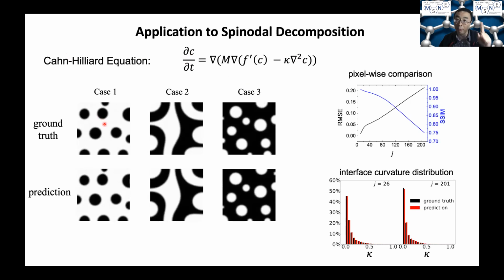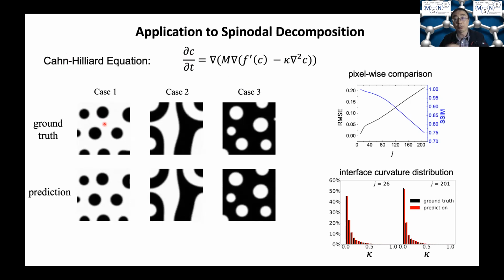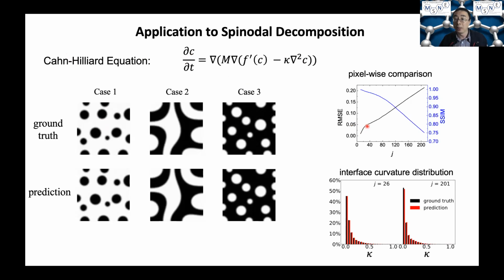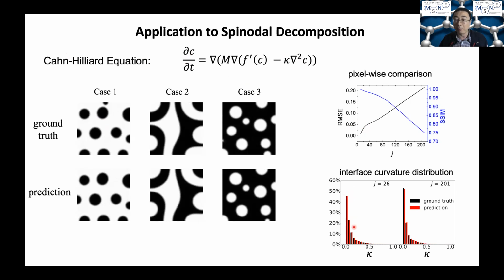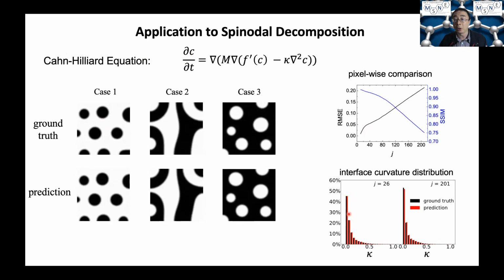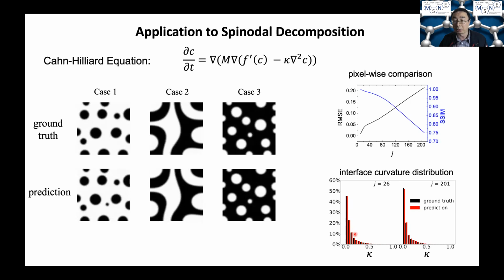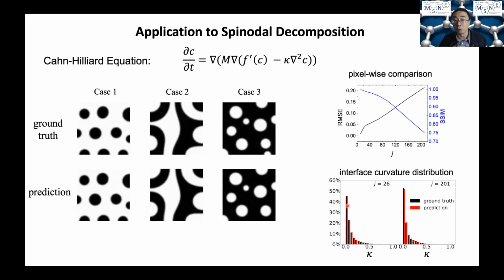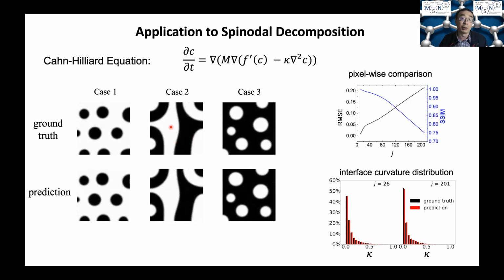When we use only 1 frame as the input, and ask the model to predict the next 200 frames, it shows an accuracy which is comparable to grain growth, and also shows very good agreement in terms of the statistical property of the microstructure. So here, for example, it has very good predictions on the interface curvature distribution for this biphasic spinodal structure.